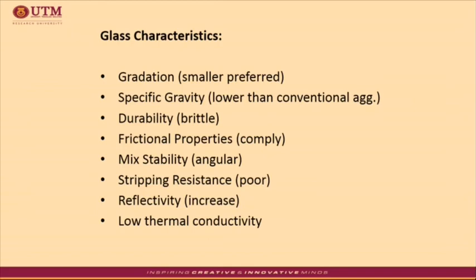In terms of frictional properties, the skid resistance tested for the mixture containing glass was found to comply with the standard. And then mix stability. The angular shape of the glass and high friction angle contribute to good lateral stability. And then in terms of stripping resistance, the glass is not absorptive and adhesion with asphalt binder is very poor. Therefore, it needs an anti-stripping agent of at least 2% hydrated lime.